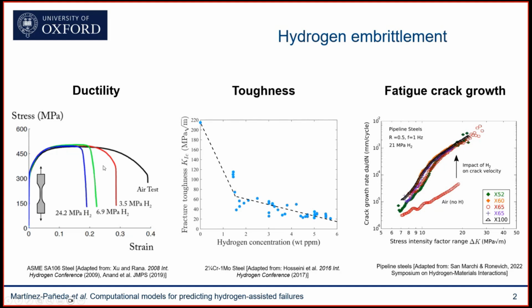You can see here, for example, uniaxial stress-strain curves, and you can see that by exposing metals to hydrogen gas, we get a very significant reduction in the failure strain. This is for a pressure vessel steel, and you can see that the fracture toughness of this material degrades by at least an order of magnitude, from more than 200 megapascals square root meter to below 20 megapascals square root meter, just by including 6 parts per million of hydrogen. And here, these are Sandia experiments on pipeline steels, and you can see that just 21 megapascals of hydrogen gas are sufficient to increase by orders of magnitude, in log scale, the fatigue crack growth rates, the speed at which cracks grow under cyclic loading.